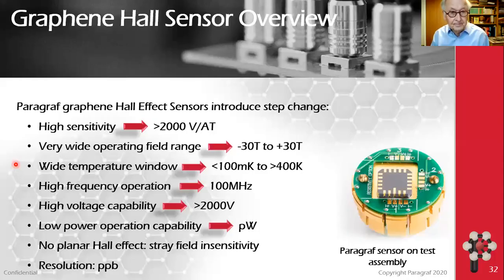This is a summary of the results: very high sensitivity, greater than 2,000 volts per amp Tesla; very wide operating field range from minus 30 Tesla to plus 30 Tesla, meaning magnetic field up or down doesn't matter; wide temperature window, works from 100 millikelvin up to at least 400 Kelvin; high frequency operation, works up to 100 megahertz; high voltage capability, you can put mains voltage on and it won't blow it, whereas this blows most other Hall sensors; you can put 2,000 volts on and it's capable of withstanding that; picowatts power consumption, very small power consumption, no planar Hall effects, and parts per billion resolution. This is a photograph of one of our Hall sensors, an earlier version, on test.